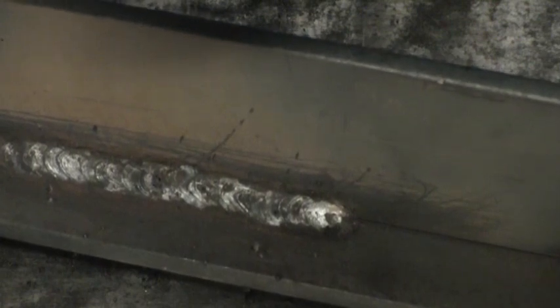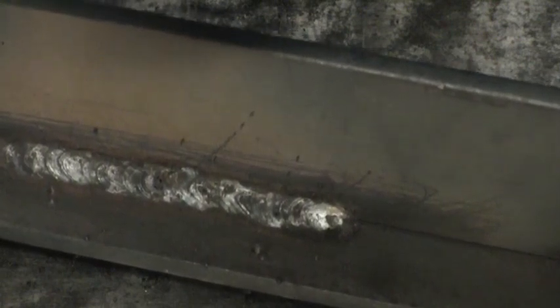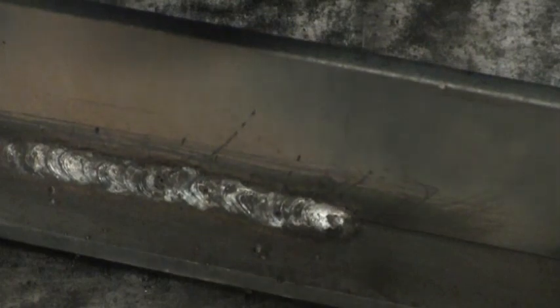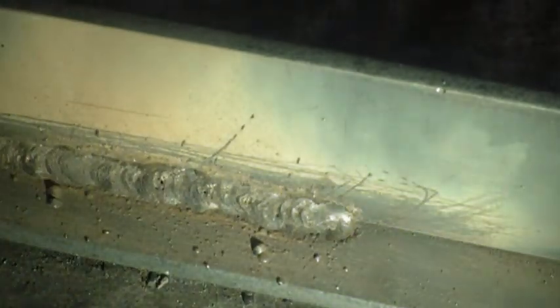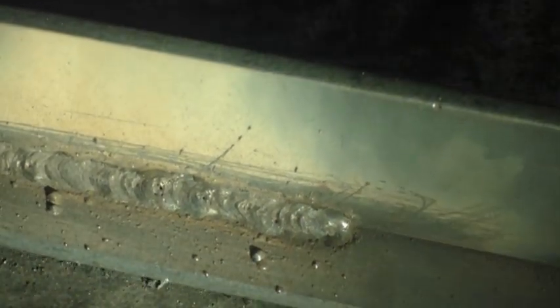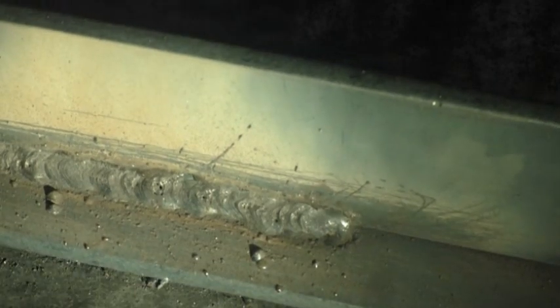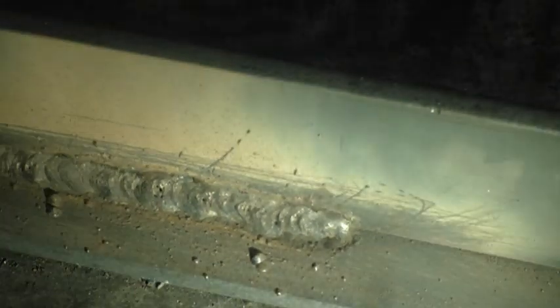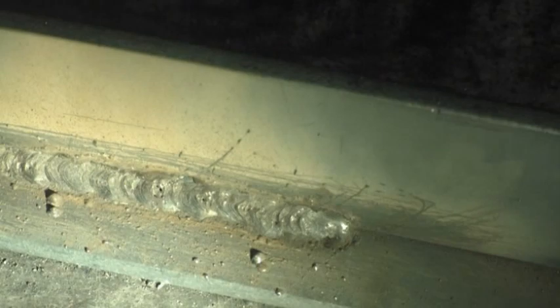And the reason I have porosity is because I don't have any shielding gas protecting the weld. There you can see it quite clearly with the flashlight. Okay. I also have a lot of spatter. All these little balls hanging out, stuck to the plate, are called spatter. And I have undercut, which is unfilled areas at the toe of the weld, and that's what makes it difficult for me to remove the slag.